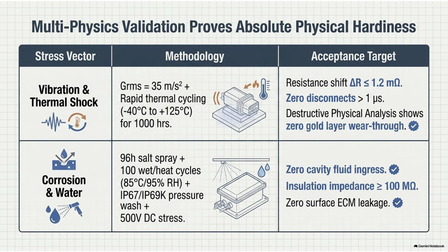And while all this physical and thermal violence is happening, they have highly sensitive oscilloscopes actively monitoring the continuous low-voltage tripwire. The absolute passing criteria to graduate this test: after 1,000 hours of torture, the electrical contact resistance of those hyperboloid pins cannot increase by more than 1.2 milliohms. 1.2 thousandths of an ohm. Barely a whisper of measurable degradation after 40 days of shaking. And critically, during the entire duration of the test, the logging equipment must record absolutely 0 microdisconnects longer than a single microsecond. Not a single tiny drop in the heartbeat.